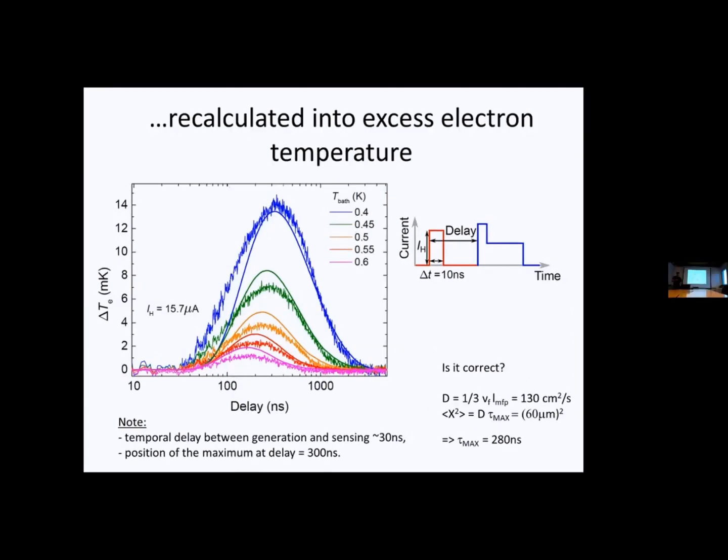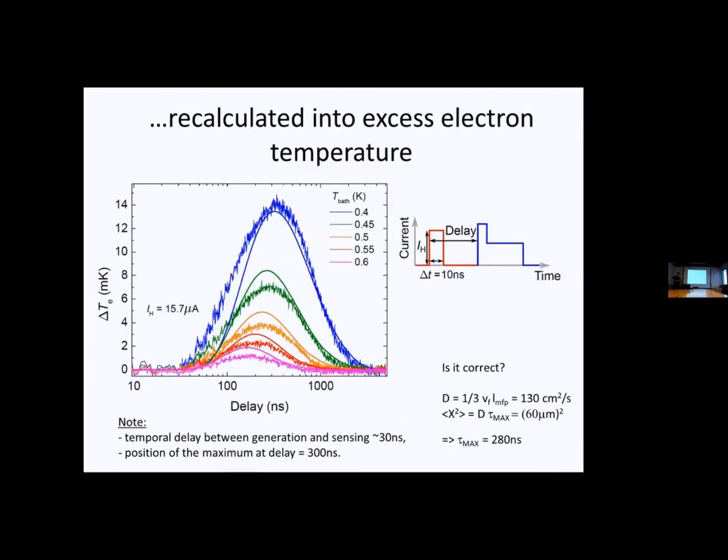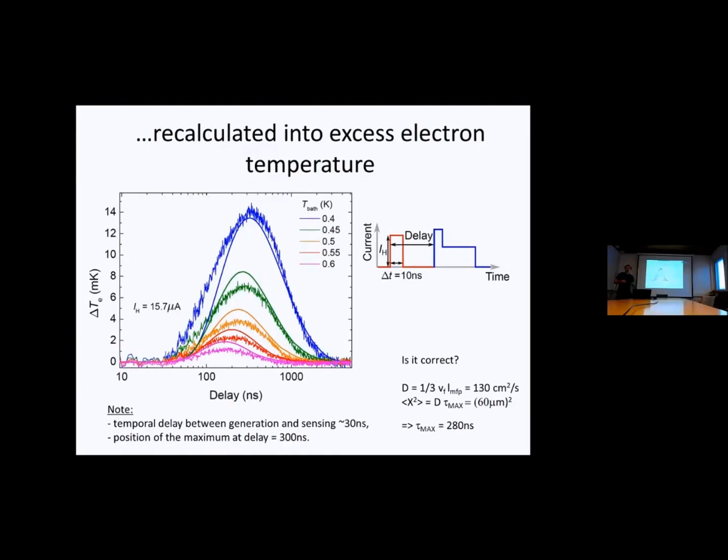So simply, these electrons diffusing from the heater to the bridge are annihilated on the way. At higher temperature, this recombination rate, annihilation rate, is much higher, so finally there are only a few of them arriving. And also, if you just take this onset, this should give you the idea, if you use the free particle diffusion model and take the diffusion constant, okay, normal state.